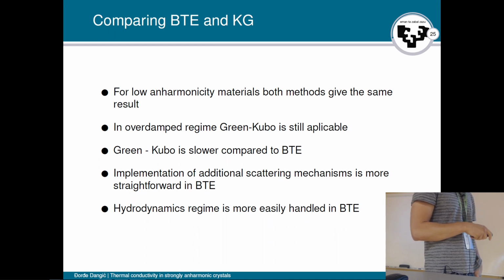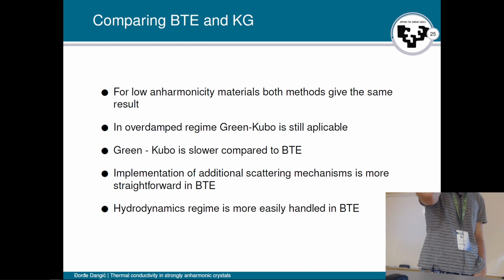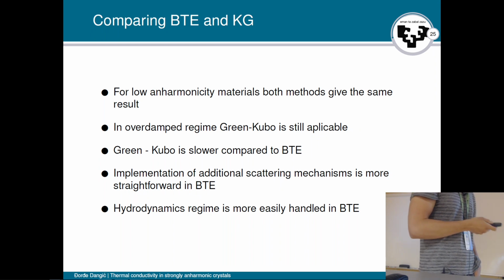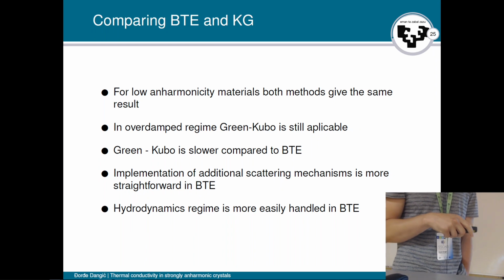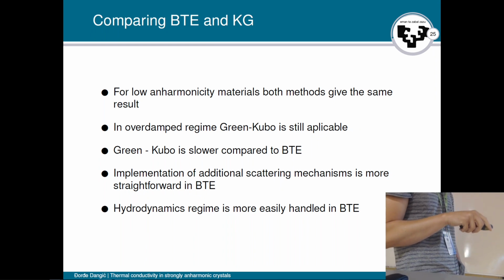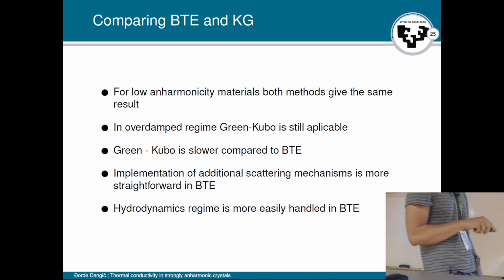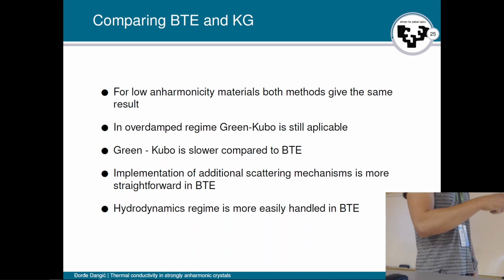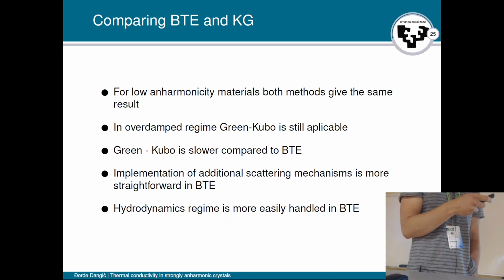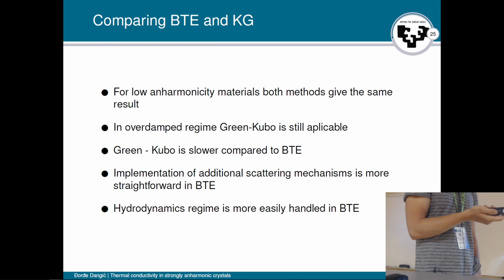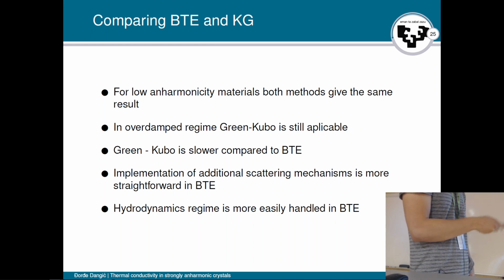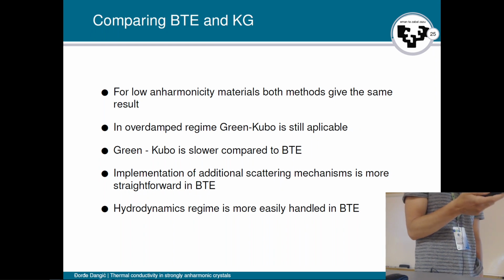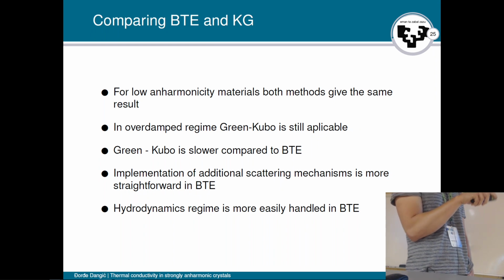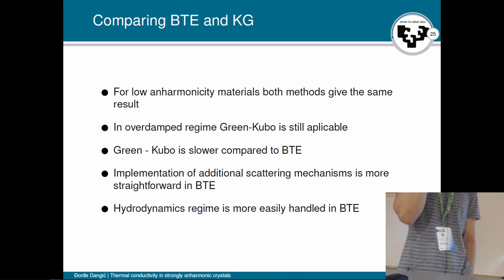Another important regime that I have not been discussing here, because it's usually not important for highly anharmonic materials, but we had a talk yesterday that says otherwise, is the hydrodynamic regime, which is usually important at very low temperatures. This regime is more easily handled in the Boltzmann transport equation. In the Boltzmann transport equation, you basically solve it self-consistently and get these numbers, while in the Green-Kubo approach, you cannot do the decoupling scheme that we have been using, which made our life much easier. Okay, so this is the comparison between the methods. The bottom line is, if you don't have a potato type of spectral function, you are safe to use the Boltzmann transport equation.